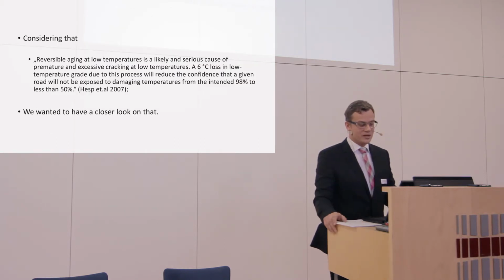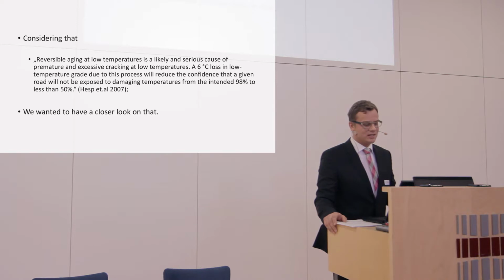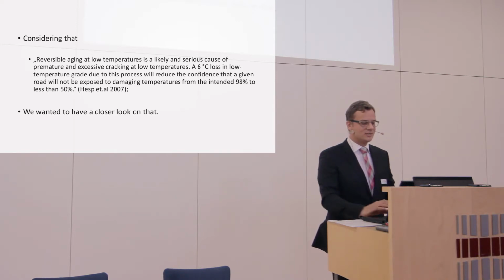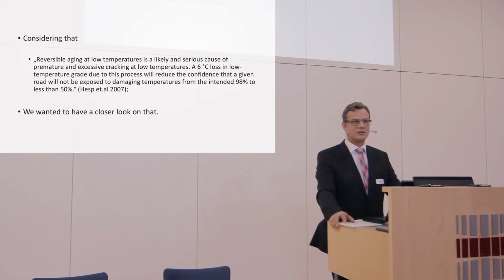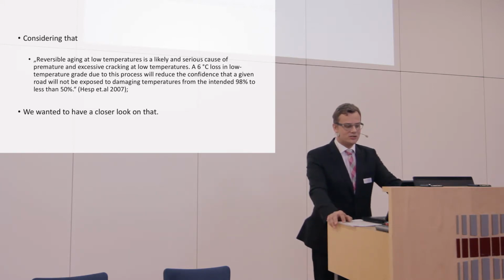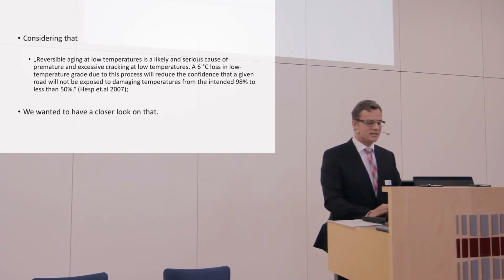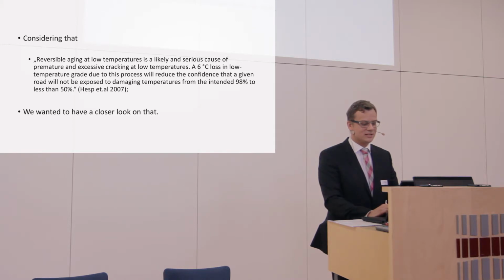But still, considering that reversible aging at low temperatures is likely a serious cause of premature and excessive cracking at low temperatures, a 6-degree loss in low temperature grade due to this process will reduce the confidence that a given road will not be exposed to damaging temperature from the intended 98%